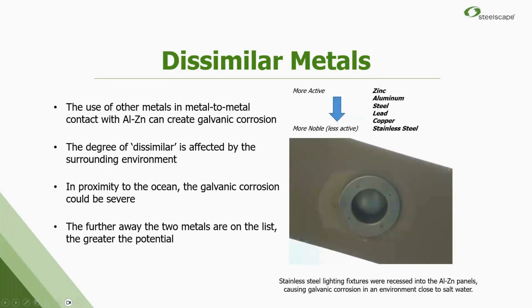More dissimilar metals. Again, this is a stainless steel lighting canister that was recessed through a Galvalume panel without a barrier, so they're in direct contact with each other. You get this ring of corrosion. It looks like the paint's failing. It's actually the substrate underneath that is failing and being corroded away, and you get this paint failure as a result of that.